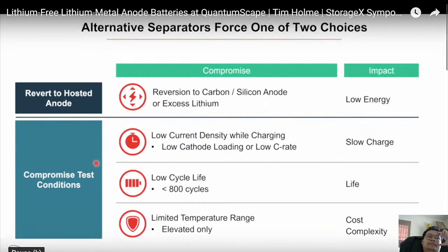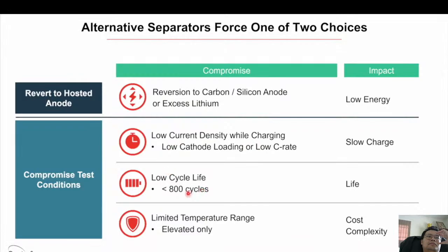Or you might have to compromise the test conditions and sacrifice some of the real world operating conditions that the automotive market expects, to go to either slow charge rates or thin cathodes, low cycle life, or limited temperature range, and, for example, run hot only. And so these are the compromises one might have to make if one doesn't have a separator that can meet all of the requirements on the last slide. So that's the landscape.